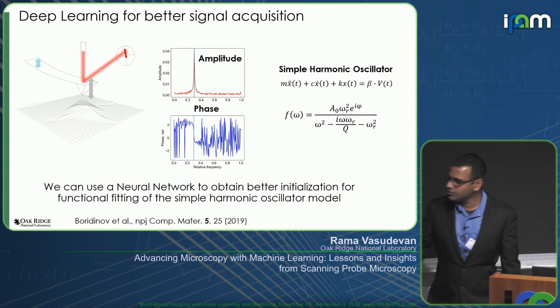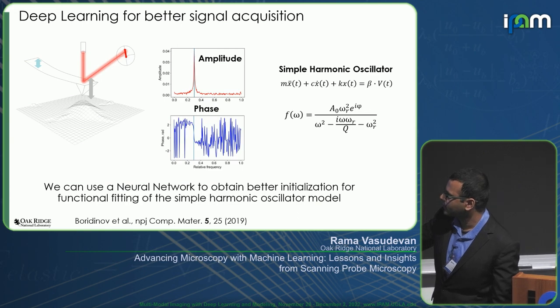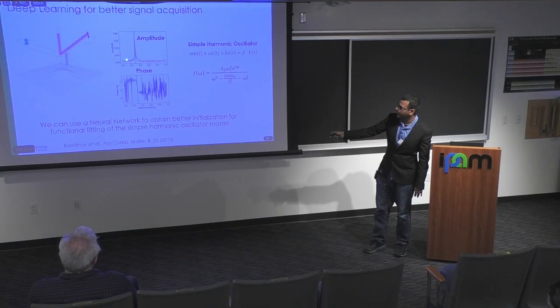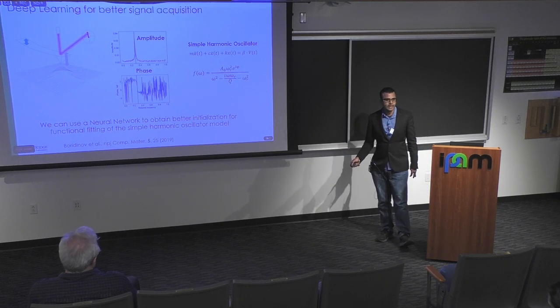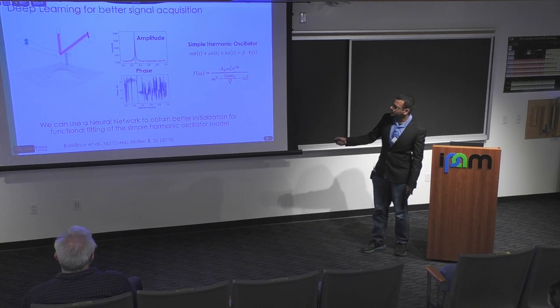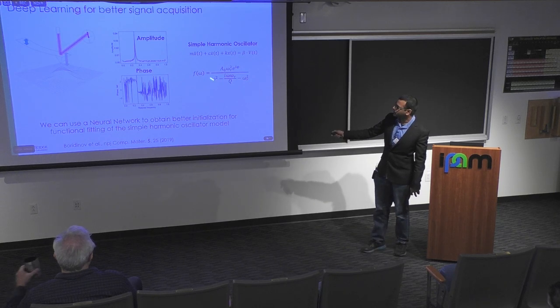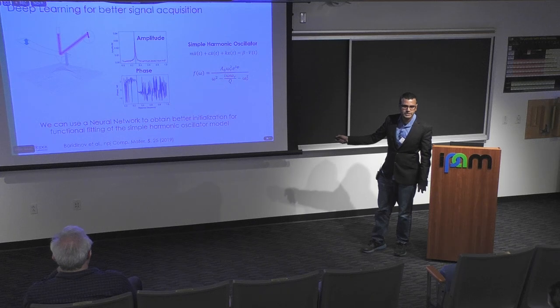And so you might ask, what is the problem with this particular model? The real challenge is that you can see here, look at the phase signal, right? And this very often happens. Even in the amplitude signal, you see a lot of noise, right? SPM is intrinsically a high noise technique. It has a lot of noise just because of the type of measurement that it is. And so the question is, how do we do this inversion for these parameters in noisy environments?